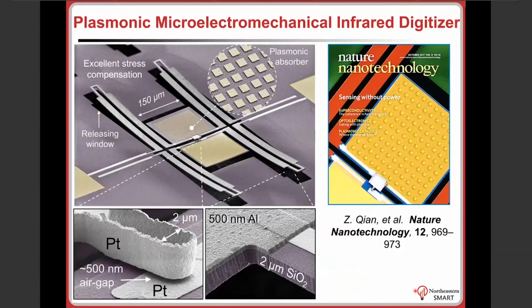Here is an SEM image of one of the fabricated devices. I want to highlight some of the important features that I've discussed so far, and you can actually see them now in this implemented device. First of all, because of residual stress in the thin film materials used to fabricate this structure, when we release these cantilevers from the substrate, the devices are anchored here at these points, but otherwise they are suspended. They're free to move. So because of the residual stress, there is a certain amount of bending moment induced in these cantilever structures.